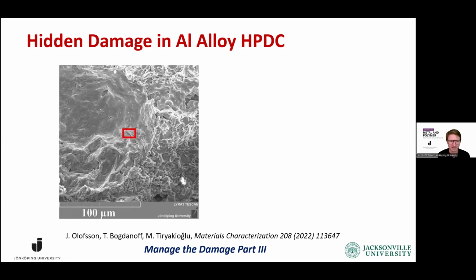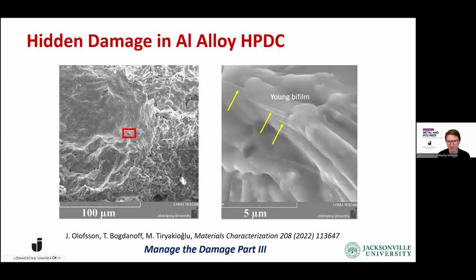When we look at the fracture surface of this sample, we see that there is a big oxide that just caused this strain concentration. And if we increase the magnification, we can see that it is clearly a young bifilm here, which is draped over the microstructure, the dendrites, which are below here of the material.